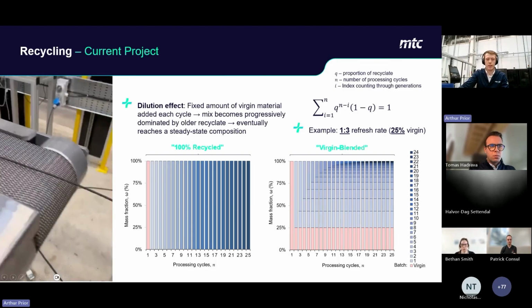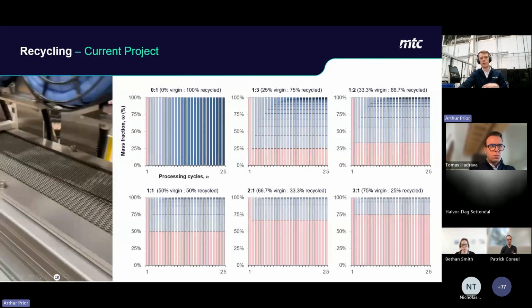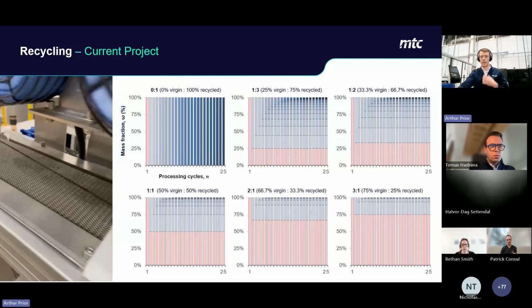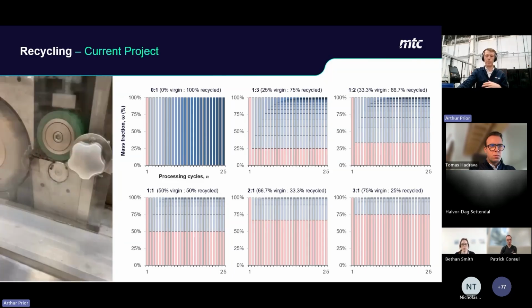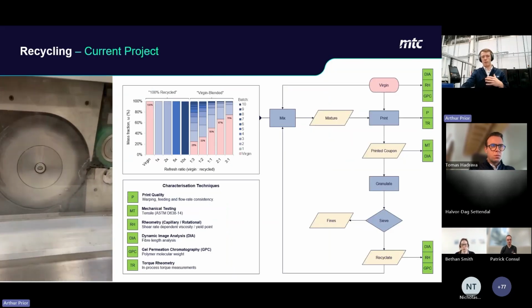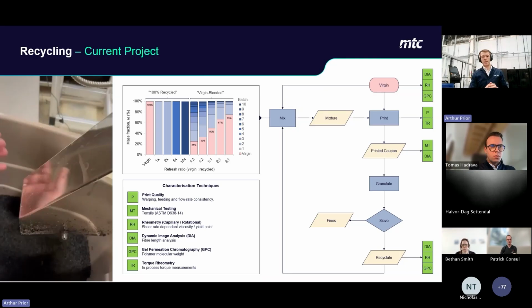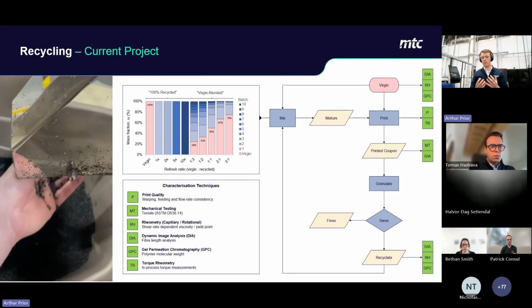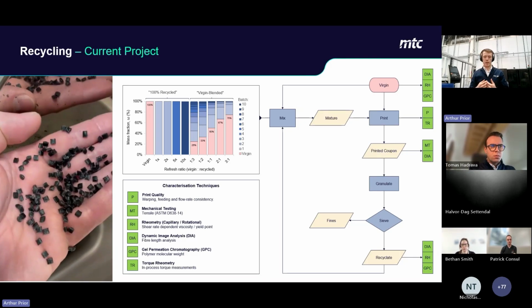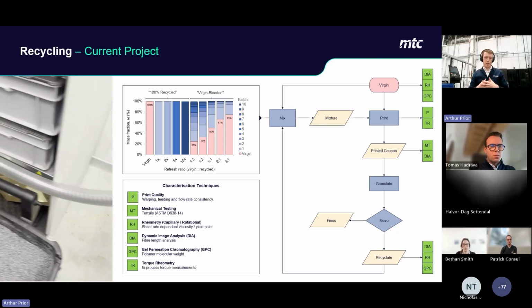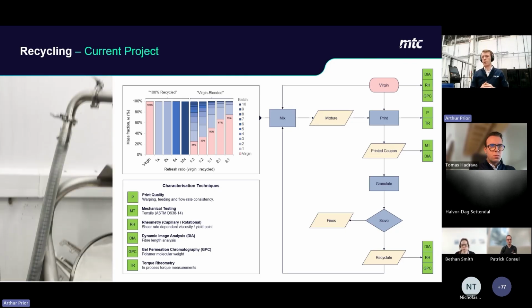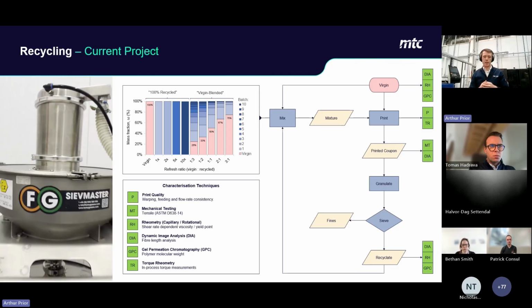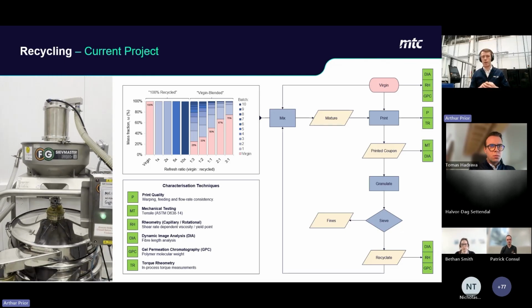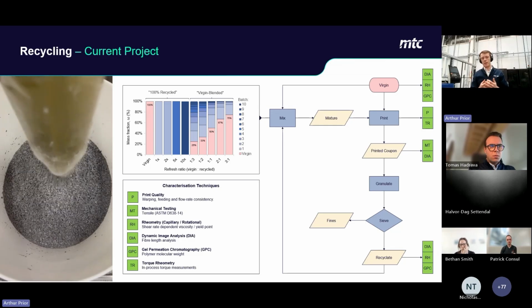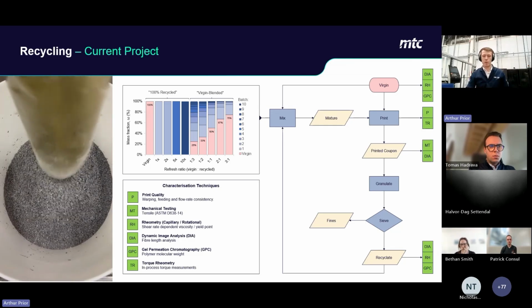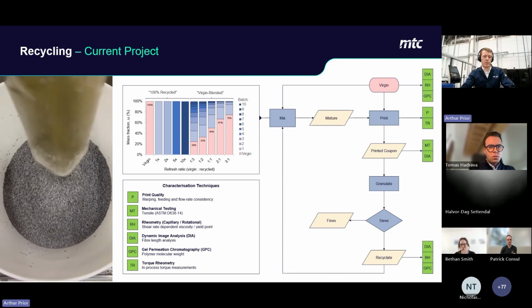So in this test campaign, we're actually evaluating 5 different refresh ratios and comparing them with fully recycled material. And because we're working with thermoplastic composites, both the polymer matrix and the reinforcing fibers will, of course, degrade. And we're interested in tracking those changes through a combination of techniques. This includes mechanical testing, rheological measurements, fiber length analysis, gel permeation chromatography, and also a print quality assessment.